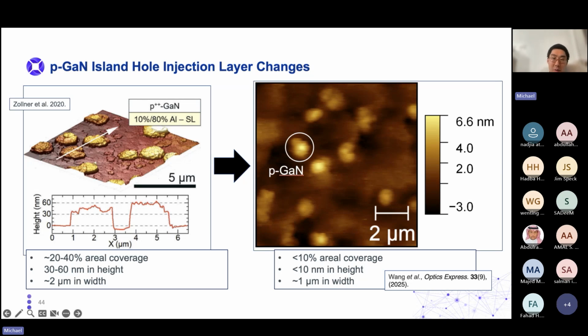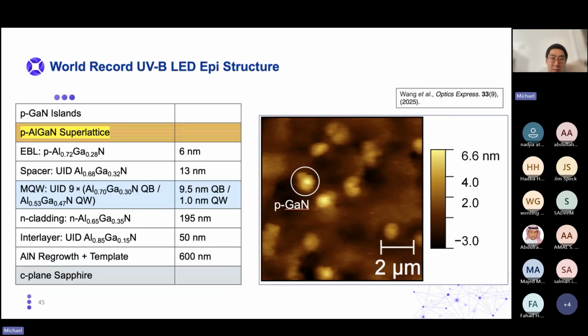So this gives more room for the light emitted from the LED to escape out the top side, and this is what we believe is the main source of this jump in efficiency that we observe. So this is the UVB LED structure, the world record LED structure that I published. So just to show, this is the same structure as before.